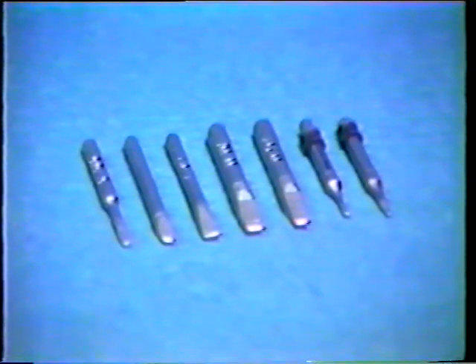In general, iron plating on copper is the best structure for a soldering tip, and because pure iron is dissolved in molten tin at a slower rate than pure copper, iron-plated tips last from 20 to 50 times longer than pure copper tips, and they require no filing or reshaping.